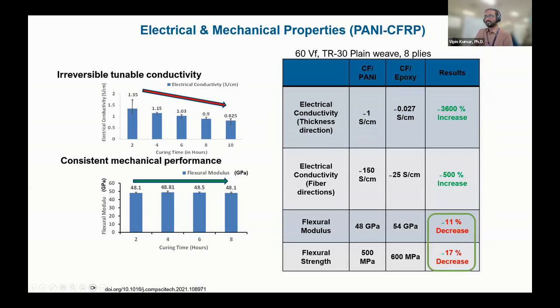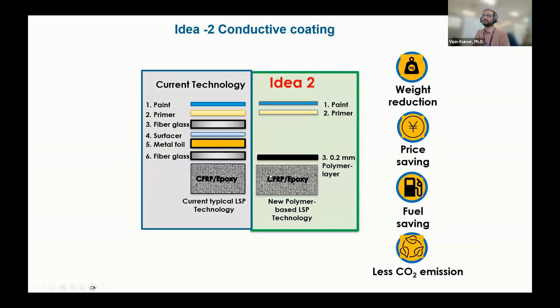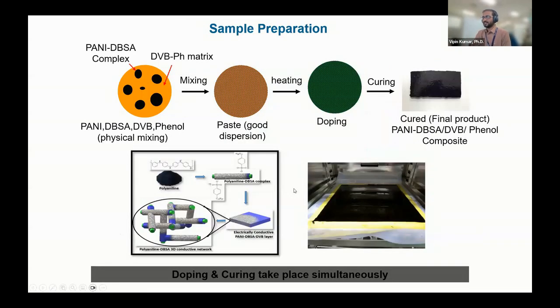So that's why there's a second method I adopted. Okay, I'm not going to change the composite laminate itself, but how about I use the same resin as a coating on top of the CFRP laminate. So it's the same method of making my coating, but rather than impregnating the fibers, I'm just putting it on top of the composite laminate and co-curing it.